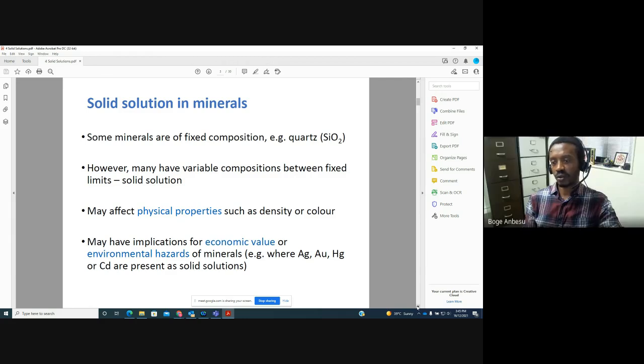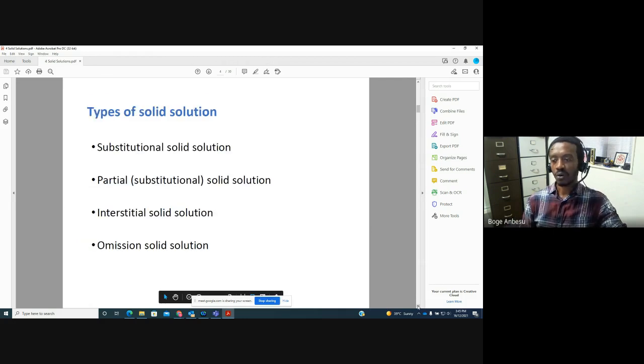If you have only a tiny bit of zinc and lots of iron, then although you say it's a sphalerite, it will be almost economically difficult to extract the zinc from the deposit. So that's why solid solutions are very important. But sometimes it may be a positive thing. Sometimes you can have gold or platinum and so on incorporated into these minerals. And if it's in high concentrations, then the gold or the platinum would be a useful byproduct. So depending on what we're talking about, solid solutions can be good or can be detrimental in a given deposit. So you could have substitutional solid solution, partial substitutional solid solution, interstitial solid solutions, and omission solid solutions. I'll probably briefly talk about each of these.